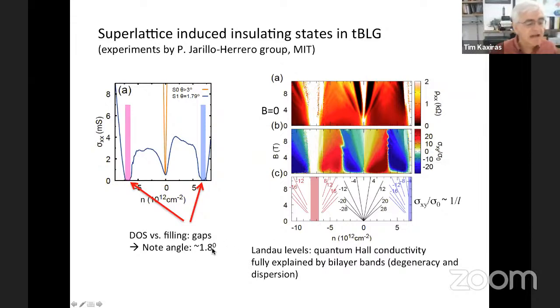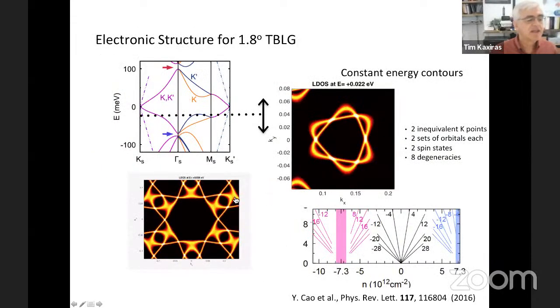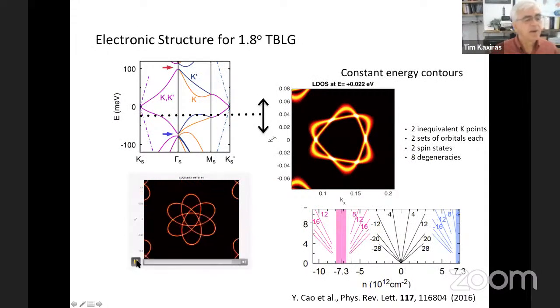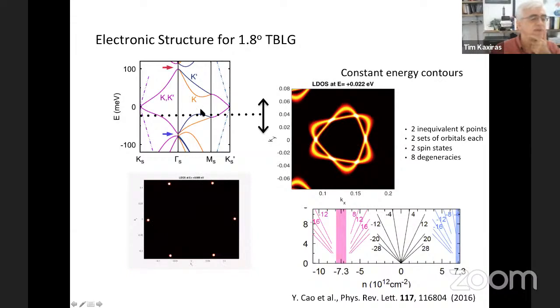Notice that the angle here is 1.8 degrees. Okay, so this is significant, and I'll come back to this. And this is verified by detailed single particle picture calculations. So this is the band structure according to the tight binding Hamiltonian. And if you take cross sections of this band structure that correspond to constant energy, you get these constant energy contours, and these give the degeneracies and fully explain the Landau levels that are measured at finite magnetic field.